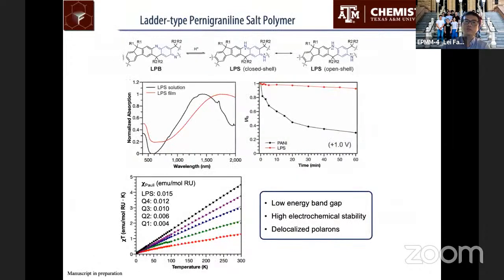And this compound again shows much better stability against acid and against strong oxidative conditions compared to conventional polyaniline. As you can see here, it could survive for over an hour at a positive applied voltage in highly acidic condition compared to conventional polyaniline. Again, this polymer shows very strong paramagnetism, and also stronger susceptibility compared to the oligomers, indicating that it has delocalized the polaron among the polymer in the solid state.